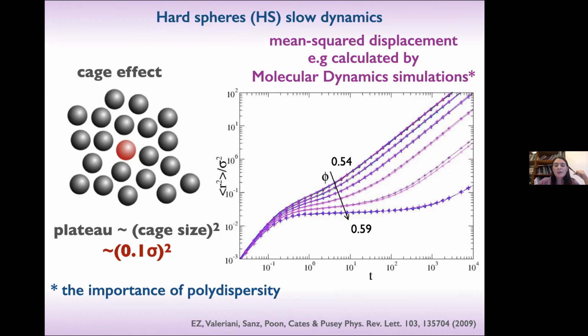The other point that I want to make is the importance of polydispersity. As I said above, in colloid experiments there is a tendency not to observe crystallization because of polydispersity, because it is very difficult to have samples that are really monodisperse. In simulation it is the opposite. If you just simulate monodisperse hard spheres at around 54, 55%, they will immediately crystallize. In the simulations that we performed in collaboration with Chantal Valeriani and co-workers and the group in Edinburgh, and Peter Pusey as well, we explored different polydispersities for these hard spheres, in the low polydisperse limit that is typically 5%, 6%, the one that is achieved in experiments.